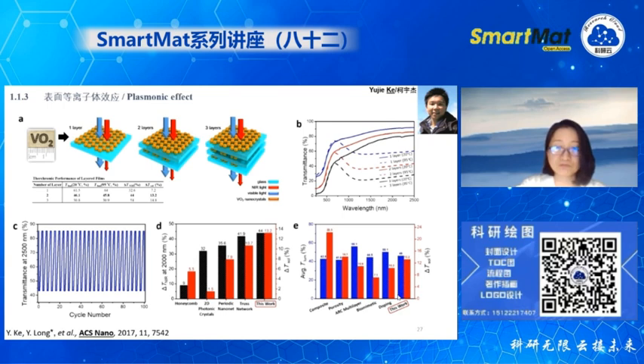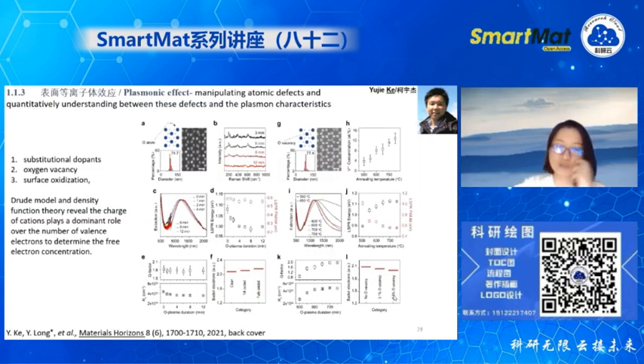Okay, by doing so, we can also get both enhanced thermochromic properties, T-room and delta T. Then my student kept continuing because he wanted to study a little bit more. He kept changing these dopants, oxygen vacancies, and oxidations. We're trying to understand these atomic defects, and also trying to quantitatively understand the relationship between these defects and the plasmonic characteristics. This paper we worked on together with Prof.